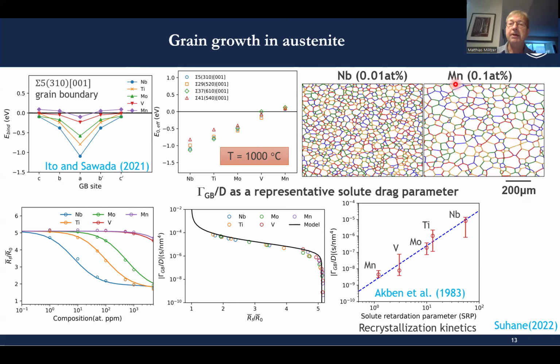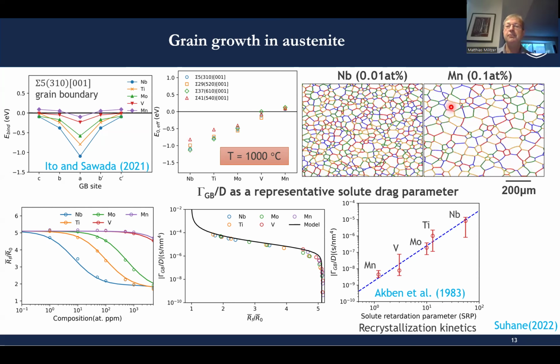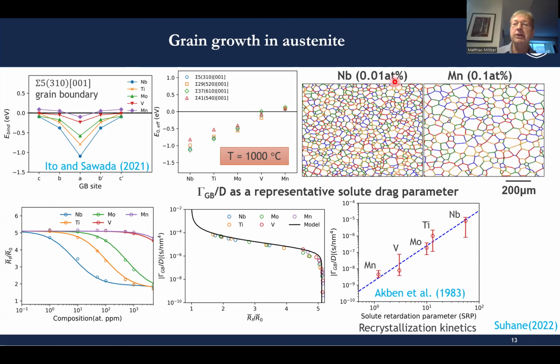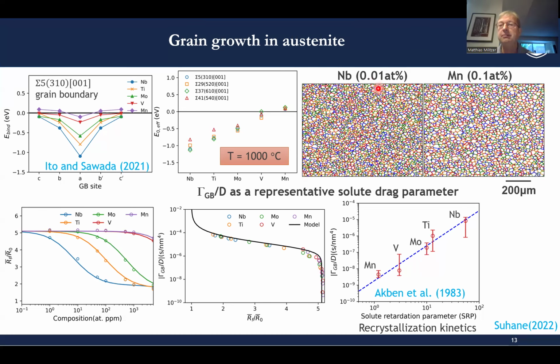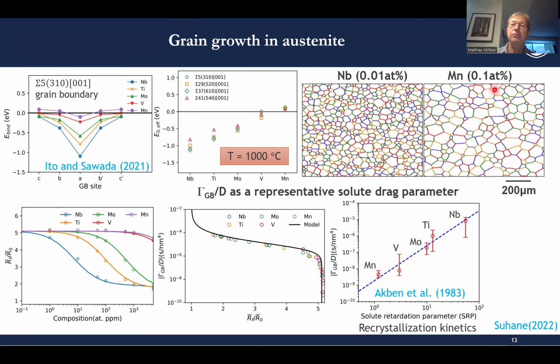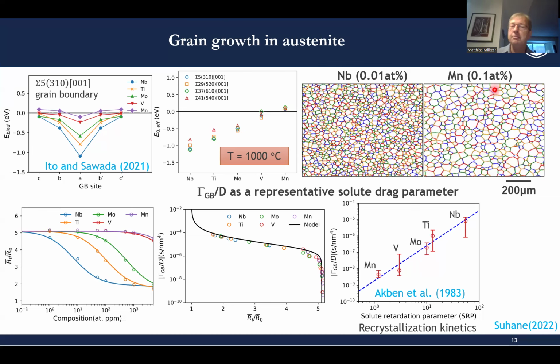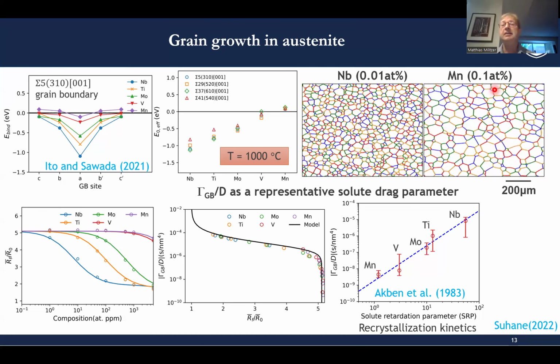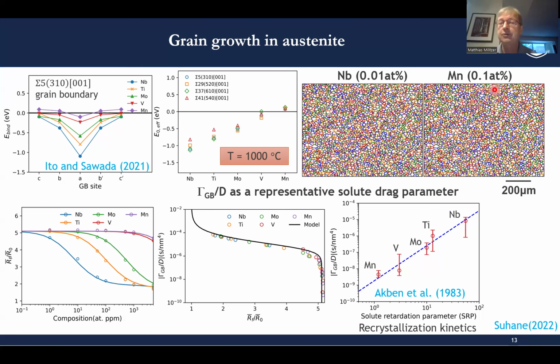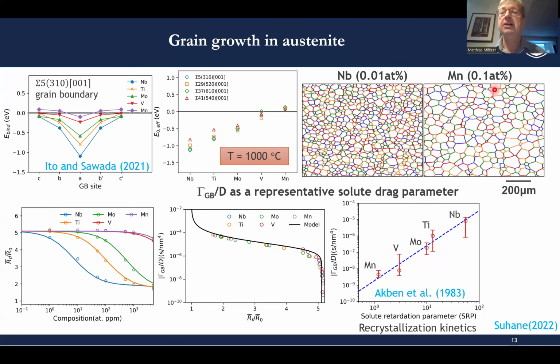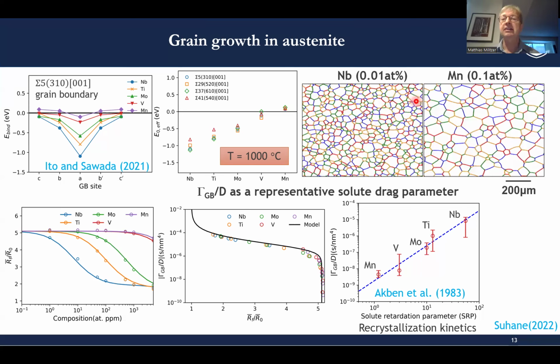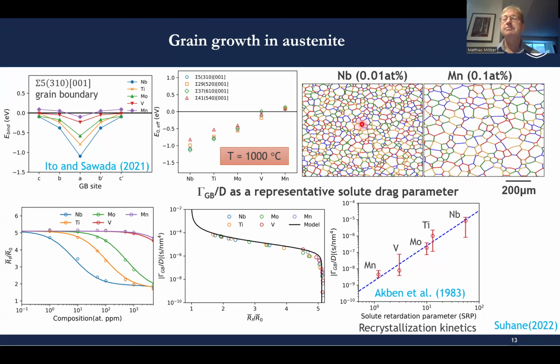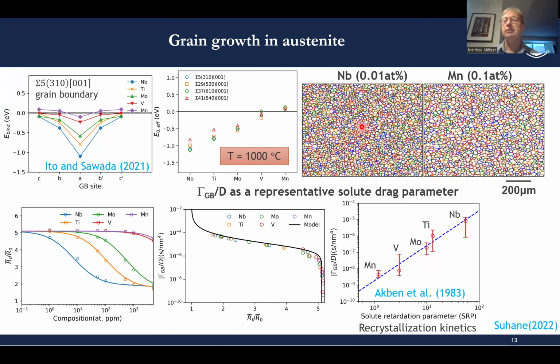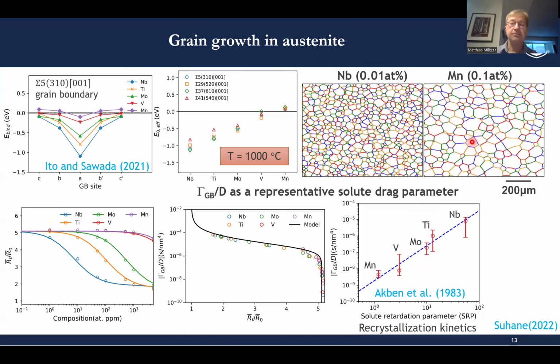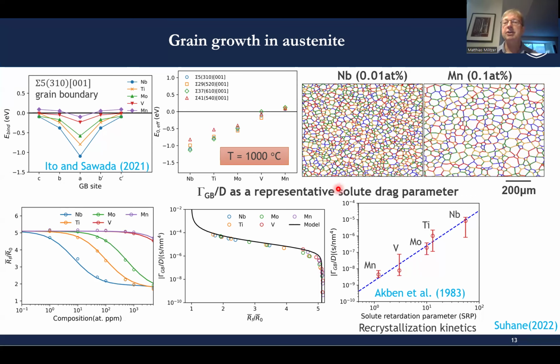And what runs here in the background are grain growth simulations from phase field simulations, one with a niobium content of 0.01 atomic percent, one with manganese 0.1 atomic percent. So these are actually compositions relatively close to what we would find in interstitial free steels, another workhorse material for automotive application. And we clearly see that adding a little bit of niobium is much more efficient in reducing grain growth rates than the manganese addition. And one can do these simulations now for different compositions, different temperatures.